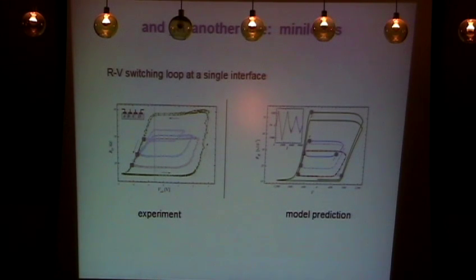So you don't need to really take care of the Poisson equation. It's immaterial. In this system, all the electronic part is completely well screened. So the important thing is that with the pulses, you move ions. These ions change the local resistance of the system. And with that, you get the effect. So that's the whole point.